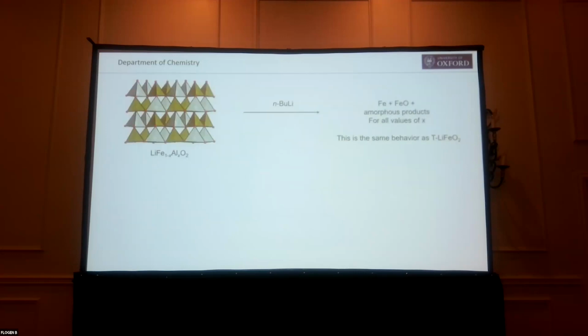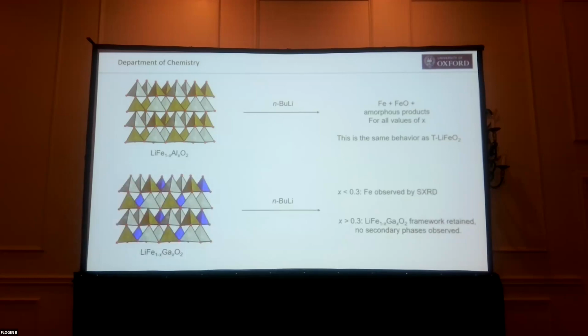What we find in the aluminium case, where we've replaced iron by aluminium, is this is a dead loss. The aluminium really doesn't help the framework. We get elemental iron forming, lithium oxide, and just chaos. The whole thing, the aluminium isn't helping. But in the gallium case, once we get more than 30% substitution, we actually retain the structure, and we can get a good crystalline material post-treatment with these reagents. So we can lithiate this material.